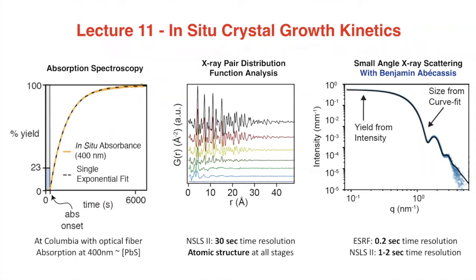And that large spacing gives rise to a smaller scattering angle. And it gives you this kind of a curve here. This curve is a small angle X-ray scattering curve, and it can be used to extract the size of the object that is scattering the X-rays.